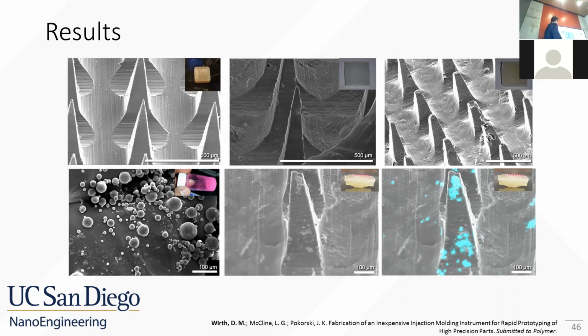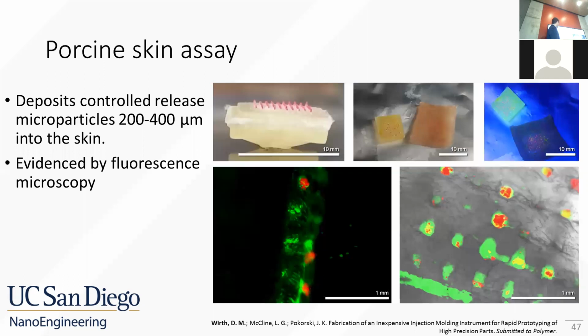These microneedle or microparticles can be used for controlled release of various drugs or nanoparticles. In this case, these microparticles were loaded with palladium for energy dispersive spectroscopy to verify that they are embedded in the tips. They were loaded with rhodamine B, a red fluorescent dye, for fluorescence imaging. The backing of the microneedle patches was loaded with FITC, a green fluorescent dye.